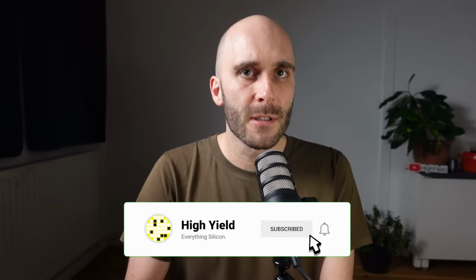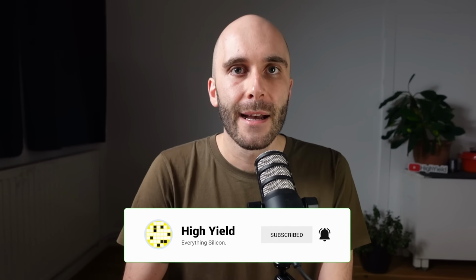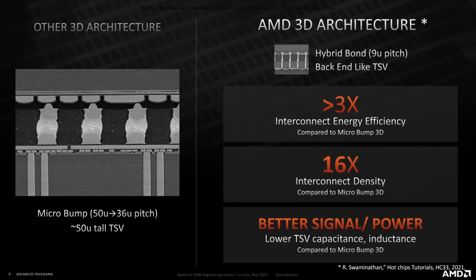Just by having more, smaller and shorter interconnects, hybrid bonding reduces resistance by about 90% compared to solder interconnects, which means the energy cost to transport a single bit is reduced. Using hybrid bonding, AMD was able to increase the interconnect density by 16x compared to an already small microbump technology.